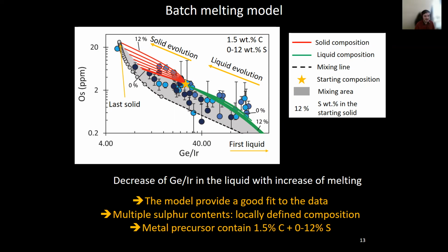And what we can see is that with a batch melting model, it is possible to fit our data. And to do that, we use a metal composition with 1.5% of carbon and from 0 to 12% of sulfur. The multiple sulfur contents suggest that the sulfur content of the metal is locally defined, probably during a heating event.